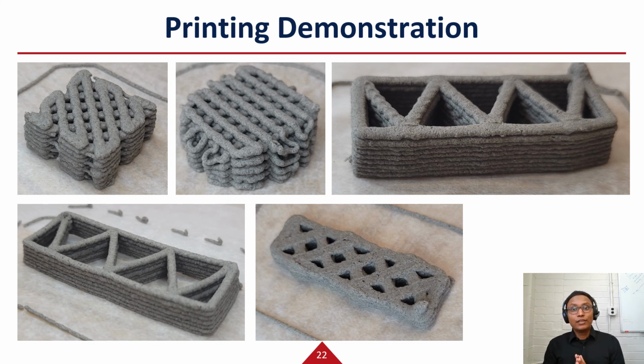We also went one step further and tested the compressive strength of these blocks. From our experiments, the maximum compressive strength that we received was 0.4 megapascal, which is similar to commercial ceramic foams with low density. We are still working on improving the strength of the printed parts.